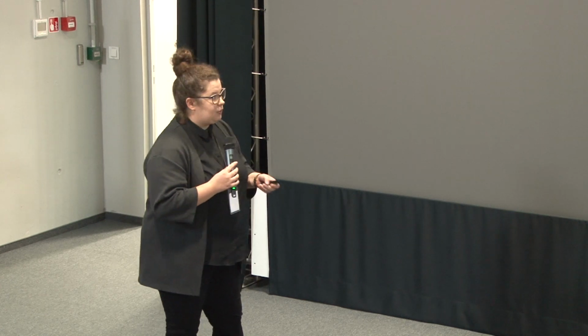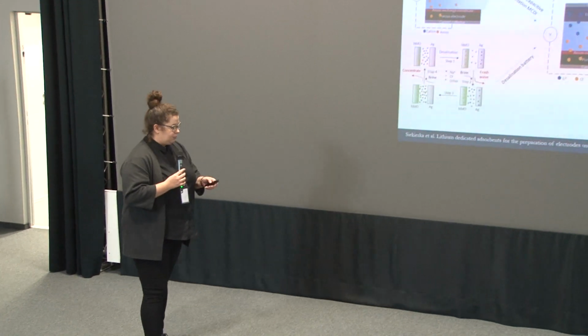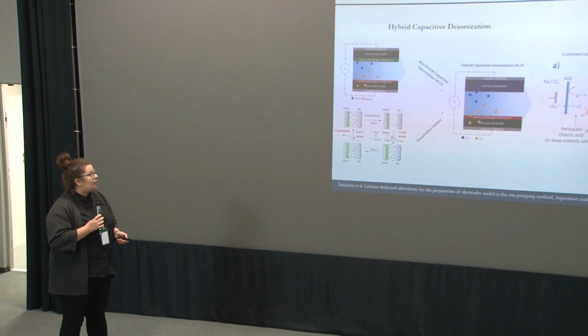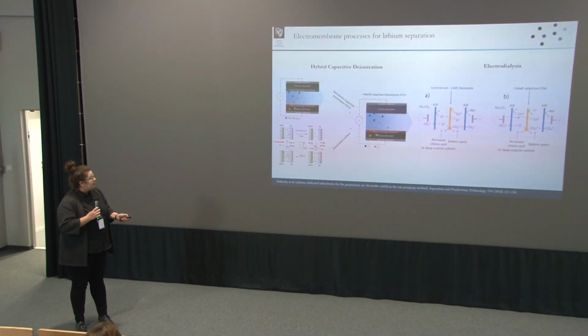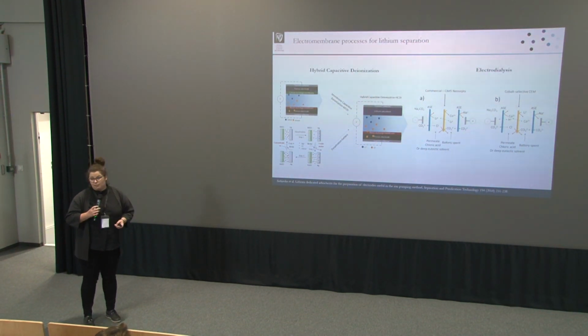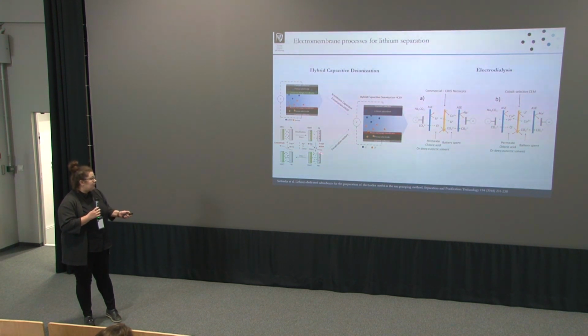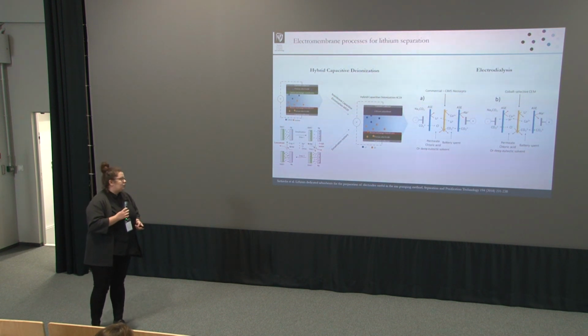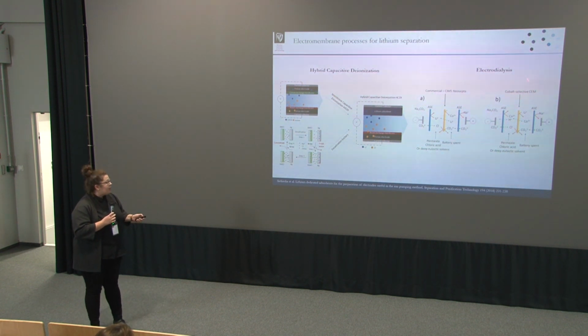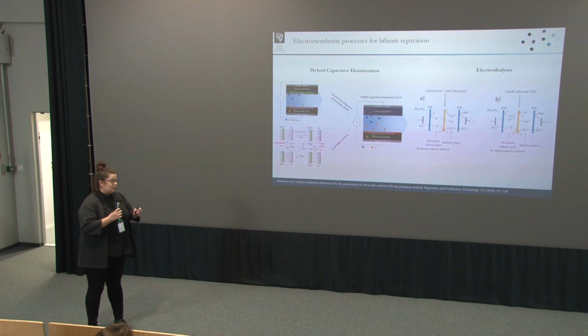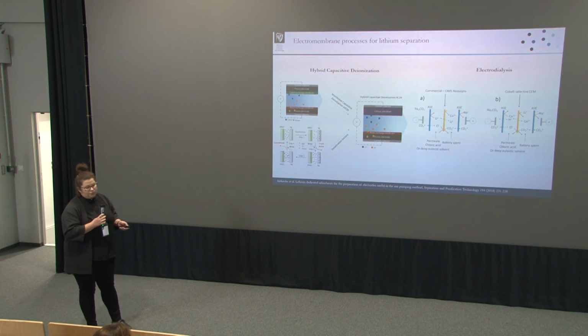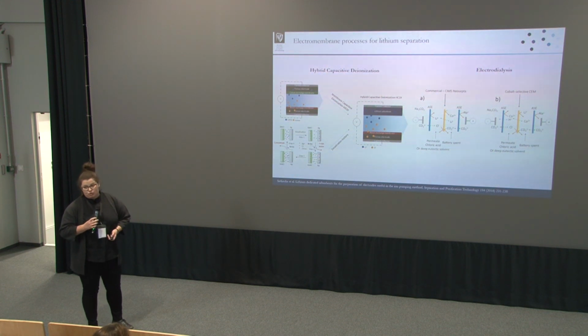For the brines, I focus on releasing lithium, rather than selective adsorption, from the multi-component mixture. I apply a hybrid system by connecting typical membrane capacitive deionization, CDI, and battery desalination. Just combine them and obtain the hybrid capacitive deionization, where we have a selective cathode dedicated to capturing the lithium, combined with an anode made of a typical porous electrode covered by an ion exchange membrane.